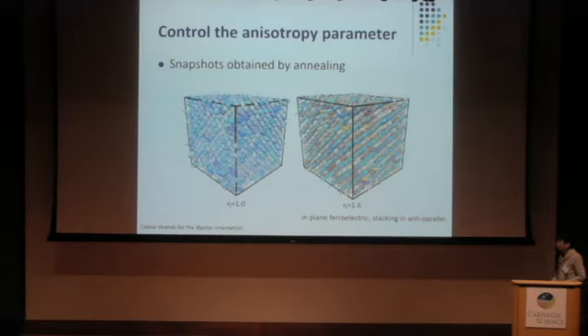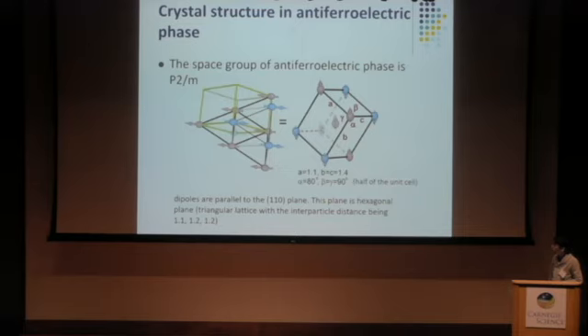And this is a snapshot of each phase, ferroelectric and antiferroelectric. These snapshots are obtained by gradually cooling the paraelectric mother phase. For the left one, the color represents the dipolar orientation, and almost all the dipoles are parallel, yielding the ferroelectric phase. And in the right panel, there is some ferroelectric ordering in the hexagonal plane, but the stacking of the hexagonal planes is in an anti-parallel manner. The crystalline structure of this antiferroelectric phase is displayed here.